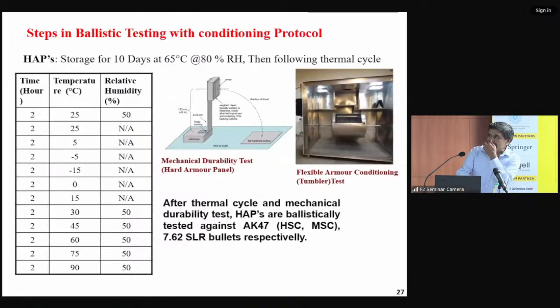So we are doing this test, and in fact about the BIS, we are doing the testing. There is a conditioning protocol for testing as per the BIS, where all the hard armor panels are exposed to a specified temperature, 65 degrees centigrade at 80% RH, with a holding time of 10 days. After the 10 days, the hard armor panels are exposed to cyclic temperature, from the lowest temperature of minus 15 up to 90. Then the hard armor panel at 90 degrees centigrade, with a holding time of 2 hours, is taken out, and this hard armor panel is dropped.